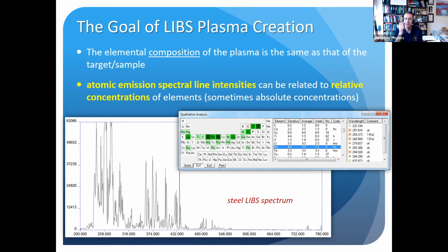With a little more work, I could tell you exactly how much of each element is in that alloy, and then that would identify the alloy uniquely. So this technique is being used really well on recycling lines. When you have all kinds of metals in there and you don't know what they are, you can shoot this laser over it almost arbitrarily fast and exactly identify what all these different metals are. It's no problem at all on metals. Harder on bacteria, but easier on metals.